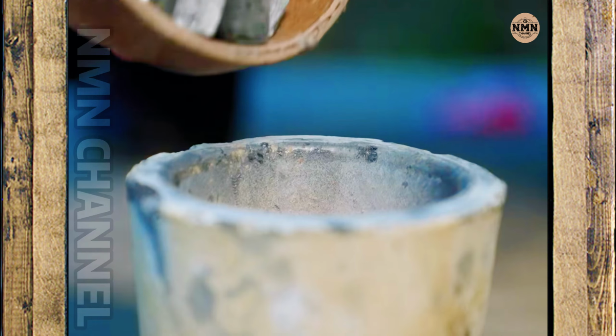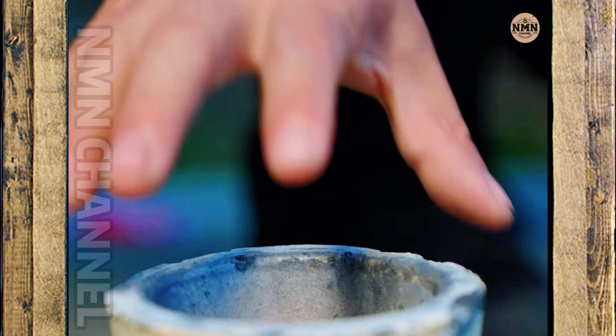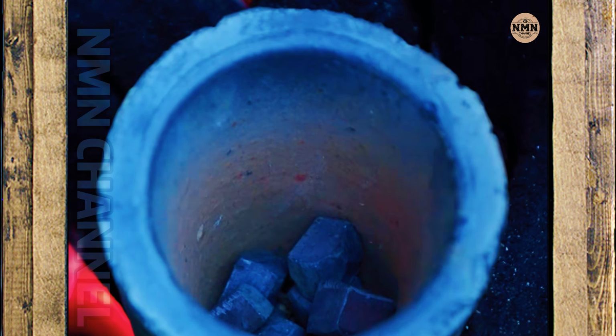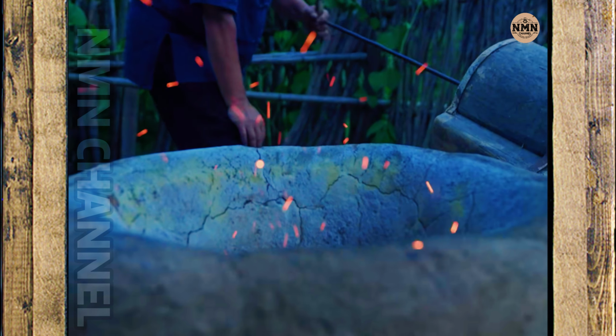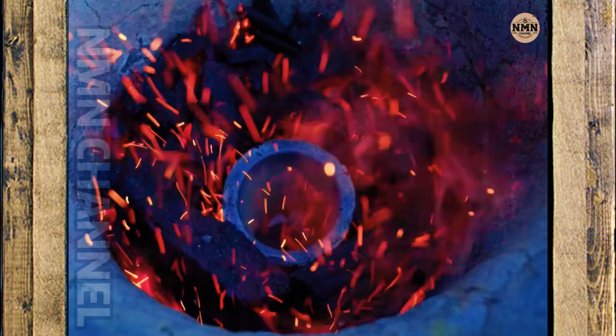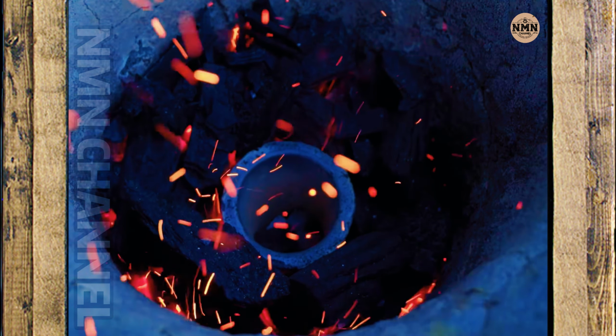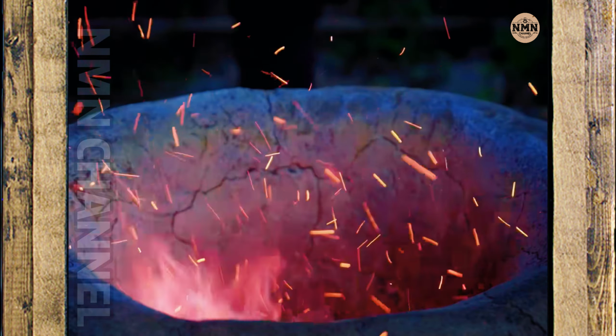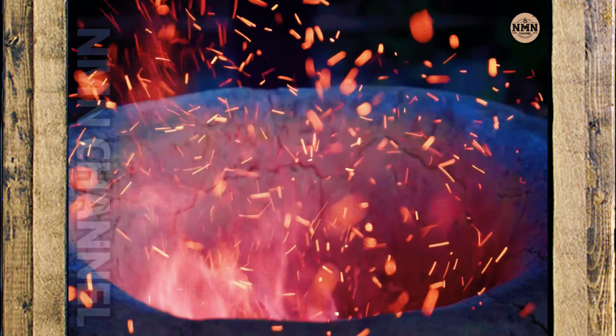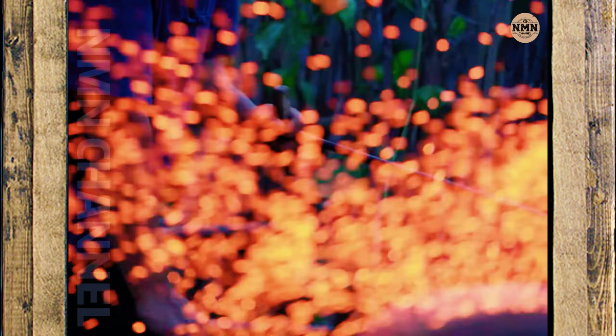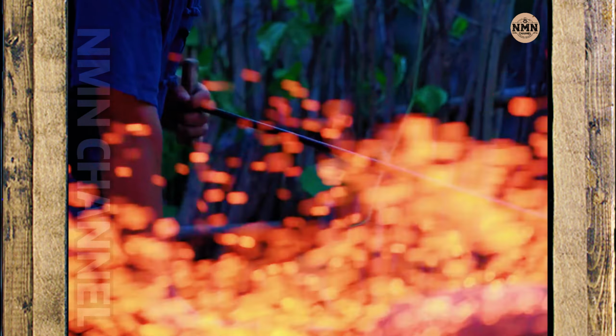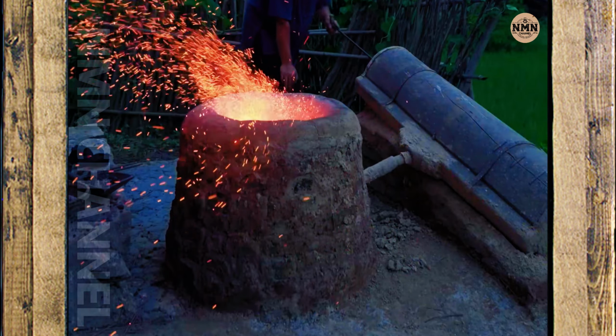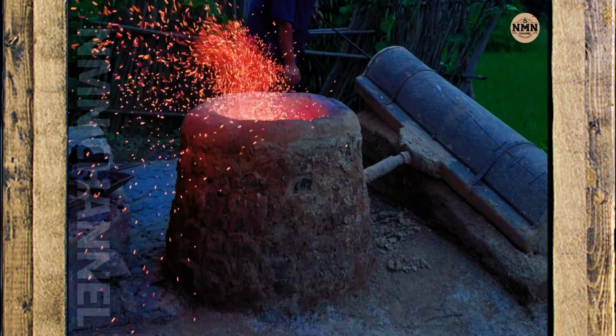The craftsman moves on to the crucial stage, smelting the lead. Lead, a heavy, soft, and easily melted metal, is used as a medium. When melted, it has the ability to absorb the silver from the ore, separating the precious metal from the rest. The craftsman puts each block of lead into the furnace, carefully controlling the fire. Too high a temperature will ruin everything, and too low, the silver will not appear.